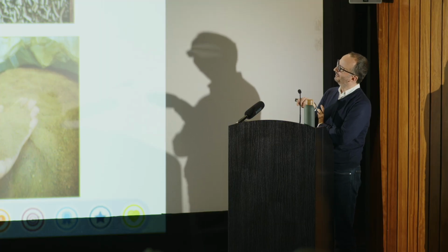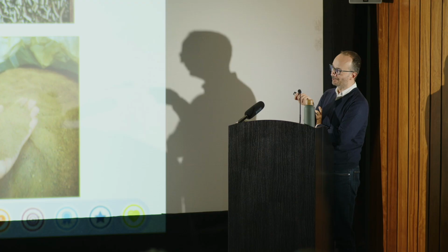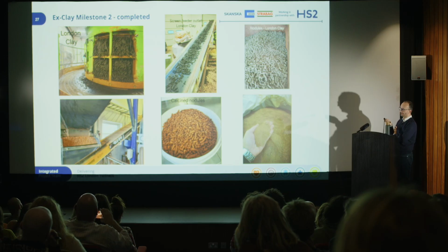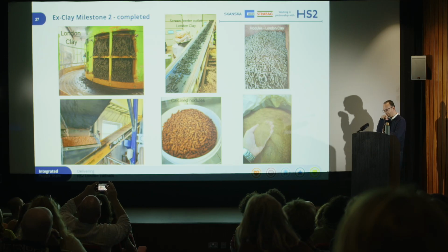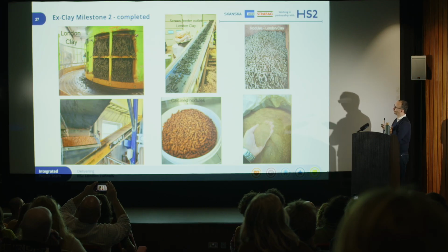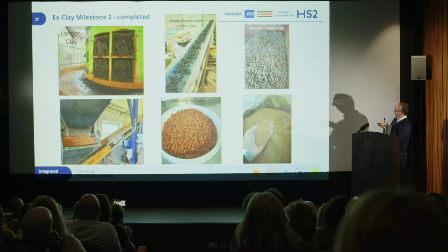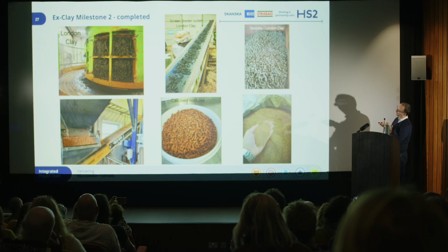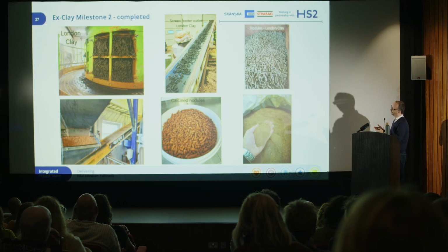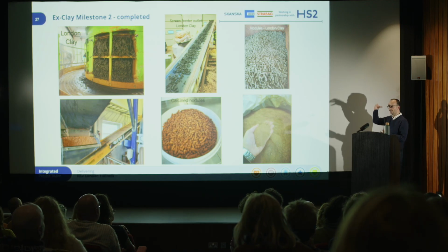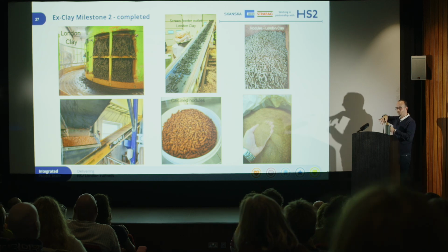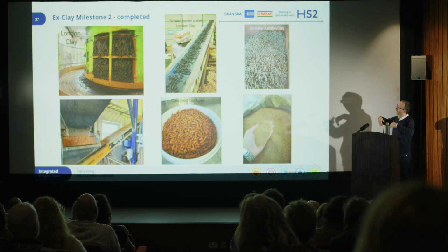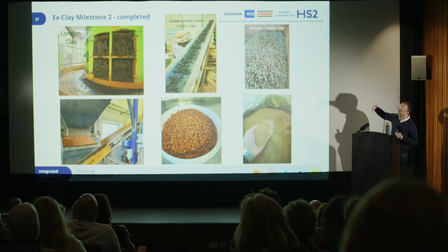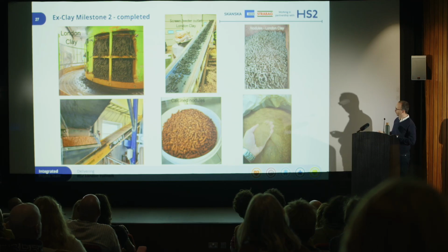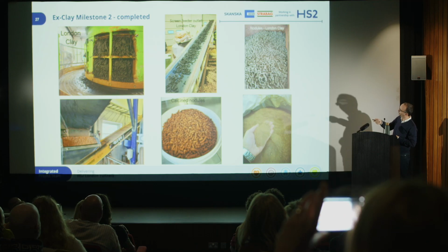So this is a bit on the facility, how they were doing the calcination, because at 42% you cannot just dry it in lumps and hope for the best. So the first picture on the top left-hand side is essentially, whoever has played with Play-Doh, you put the clay in and you compress it from the top and it comes out as nodules. And those edges, they've got something that cuts it, and you've got those small nodules that go up on this conveyor belt over there.